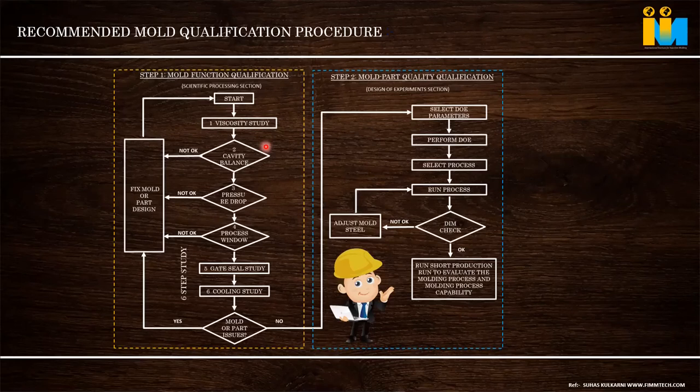If it is coming at 90 or 100 degrees, it means it is right. If it is coming above 130 degrees, it means I am not giving proper cooling. I'm ejecting it too quickly. Then there is a chance of catching in the runner, or the ejector pin piercing the part, all these things. So make a cooling time study.